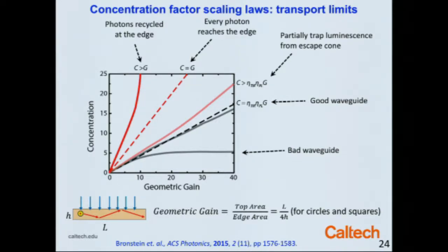So even if we have a large area, say the ratio of the collection area to the cell area is a factor of 40, we only get a concentration factor of 5 because luminescence photons are escaping from the waveguide. If we do something clever, with very high luminescence efficiency and total internal reflection, we could do a little bit better.